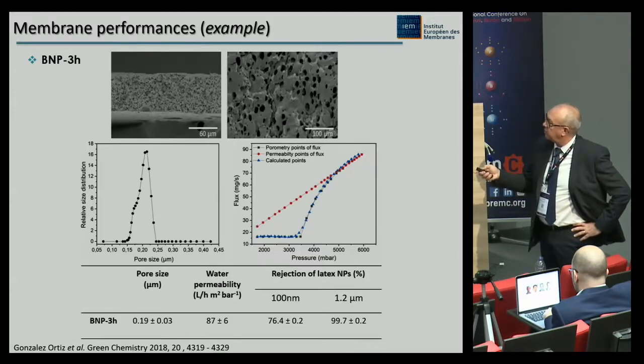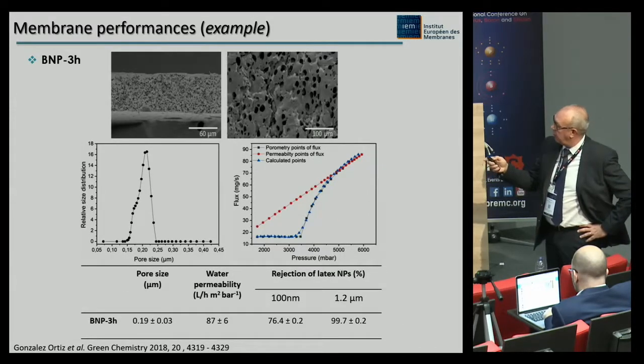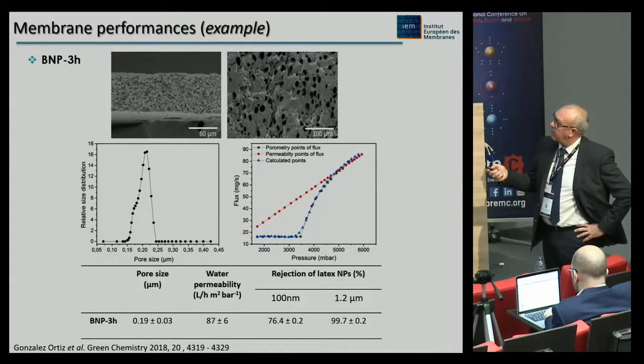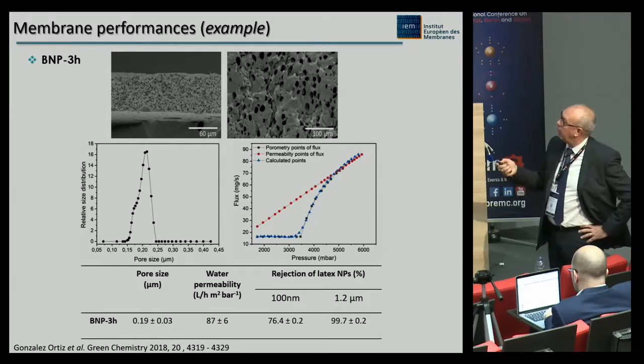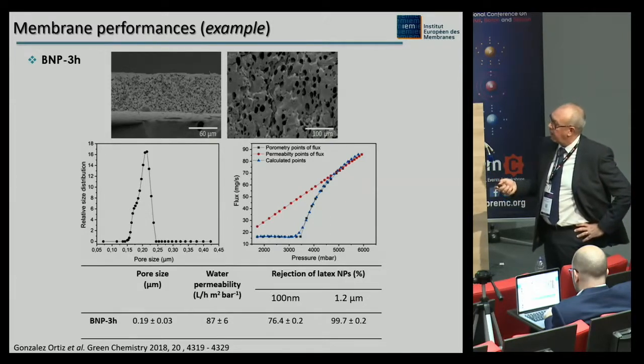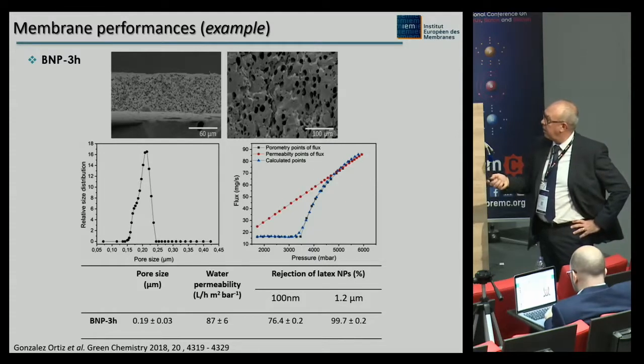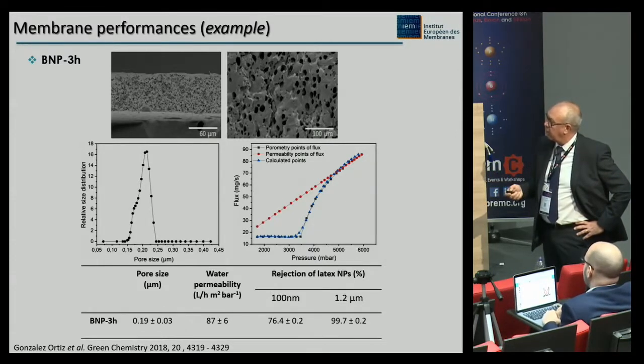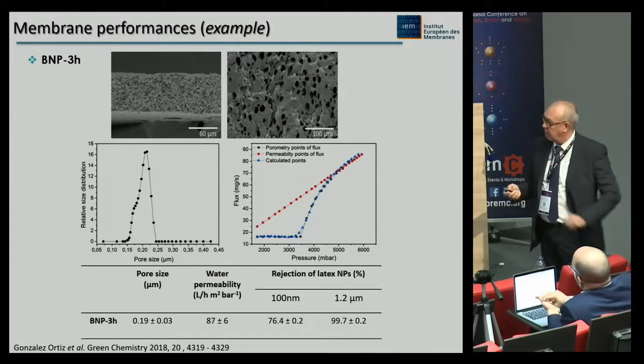And if you take this membrane after a curing time of 3 hours, you can obtain this very nice membrane also, with a pore size of 0.2 micrometers and a water permeability which has decreased largely, about 90 liters per hour per square meter and per bar. But in that case, the rejection of smaller latex particles is better, around 1 micrometer. You can reject almost 100% of the particles.